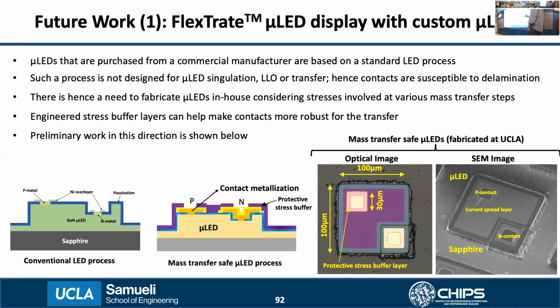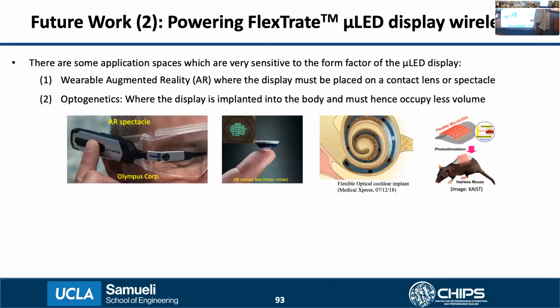which in turn helps to reduce the stresses within the contacts and prevent them from delaminating. So on the right side here, you see the optical image of the fabricated LED that we did at UCLA, where the dielectric overlaps with some region of the contacts, which helps to prevent the contact from delaminating. And you also see the SEM image of the device after singulation, where the contacts are preserved. So we plan to use these kinds of in-house fabricated devices in combination with the mass transfer approach to build flexible displays in the future.